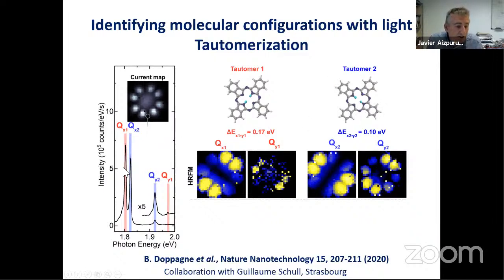They should be degenerate, but because the molecule is located on top of the metallic substrate, there is a slight tension, surface tension, an adaptation of the molecule in one of the directions that breaks the degeneracy. So QX1 and QX2 in a perfect substrate would be degenerate, but because of the substrate, they break degeneracy. And this allows you to filter the emission of one tautomer and the emission in blue of the other tautomer and see how they are orthogonal to each other when you scan and map this emission in space. So this is the experimental result.